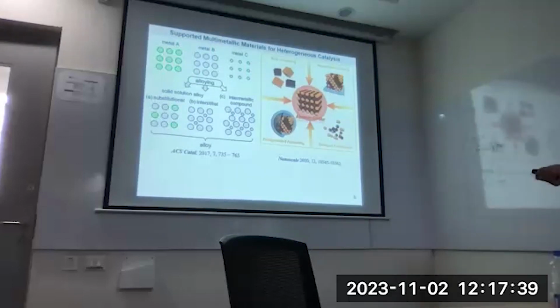So here what I did was I used encapsulation methods like silica encapsulation or metal organic framework encapsulation. Then we would keep these nanoparticles stable inside this, and we could also go to very high temperature. We had no restriction in the kind of reactions we could do.